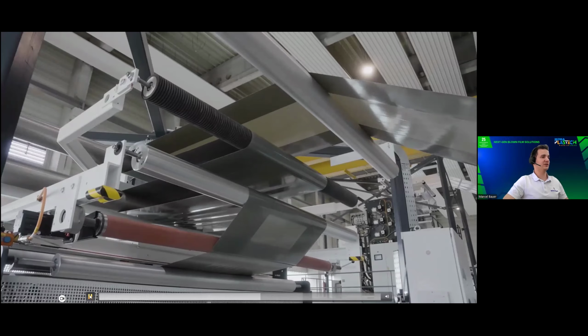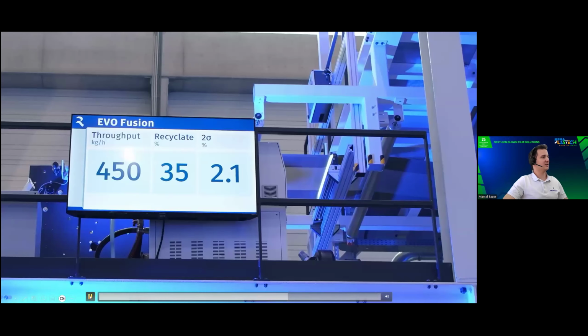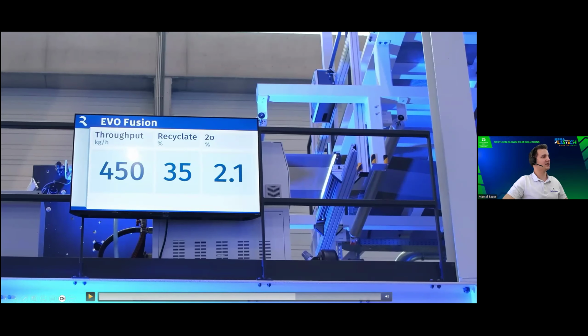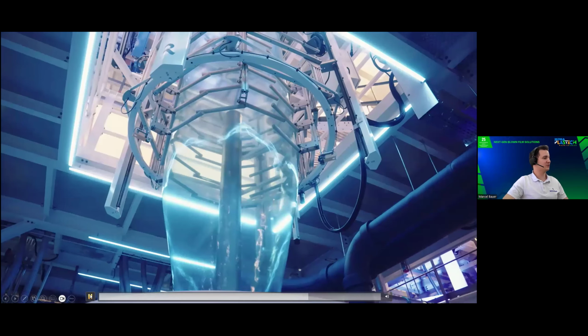On the second line here, we did run stretch hood films. So with a recycled content of 35%, PCR material from German household, and also very good profile value and output also very decent. And we run this here with a twin screw extruder. So in the core, we have a twin screw, so co-rotating two screws. And this is mainly used for better homogenization and mixture of the PCR material, because there we have different melt flow indexes and different densities. And on the skin, we have a normal single screw extruder for virgin material.